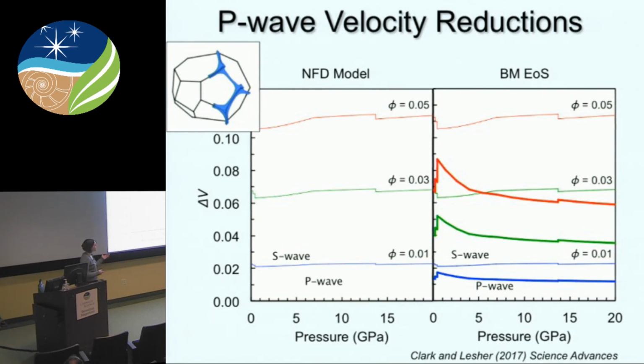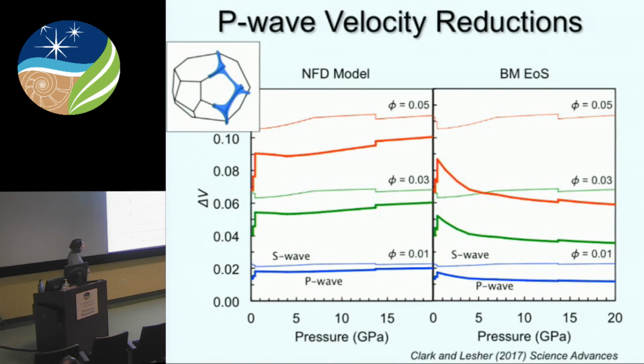So here's the Birch-Murnaghan equation of state predicted velocity reductions. And what you can see is that, again, as we increase melt fraction, we get an increase in the velocity reduction. But also what you can see here is that there is this strong pressure dependence on the P-wave velocities as a function of pressure. In contrast, for the network flexibility model, what you can see here is that we have these relatively pressure-independent velocities that also increase with increasing melt fraction.